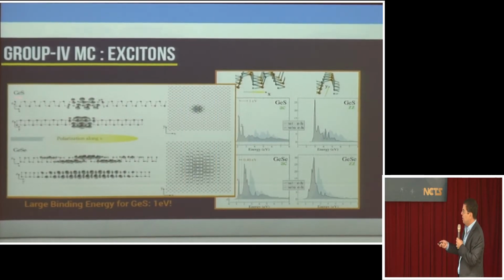So this is an example of these calculations. This is for, say, germanium sulfide. This is how an exciton looks like. It's more like a Frenkel exciton. You go for germanium selenide, so you change the chalcogen, and you go to a Wannier exciton. So a simple difference of substitution of selenium and sulfur actually changes completely the binding energy and changes the nature of the exciton state.